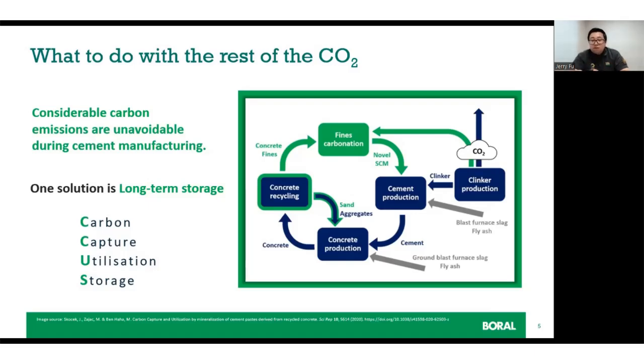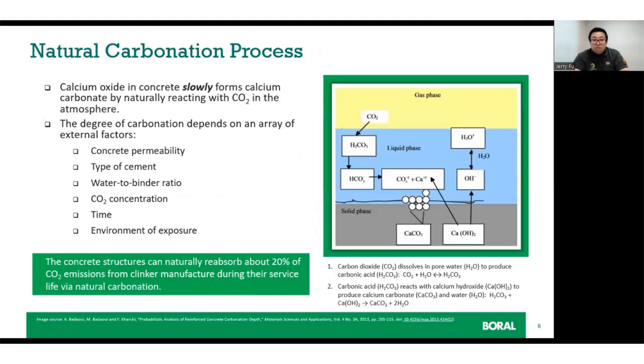One way to store the CO2 in our concrete material is a process called carbonation. Recycled concrete contains alkaline minerals in the attached mortar that are ideal for carbonation, and is then used as upcycled aggregates in concrete, preserving our natural resources. This process works by having cement hydrated products gradually reabsorb CO2 from the atmosphere through a physiochemical process called carbonation.